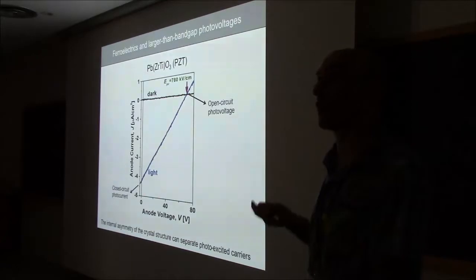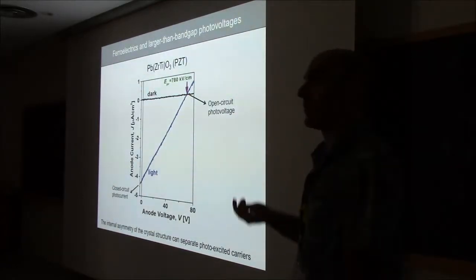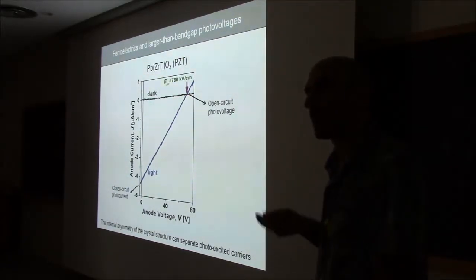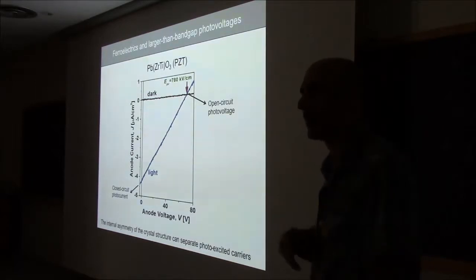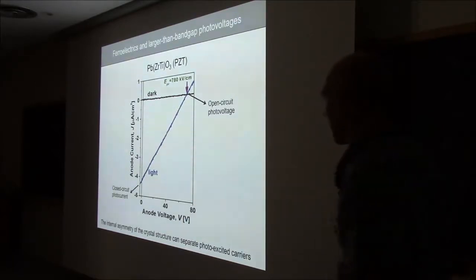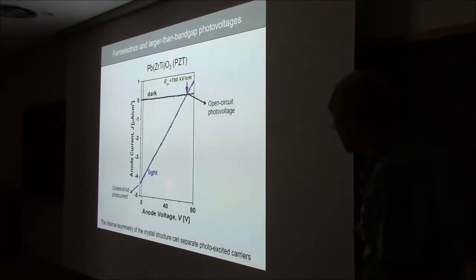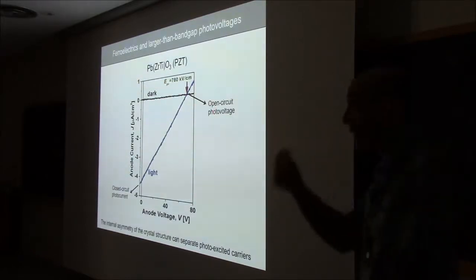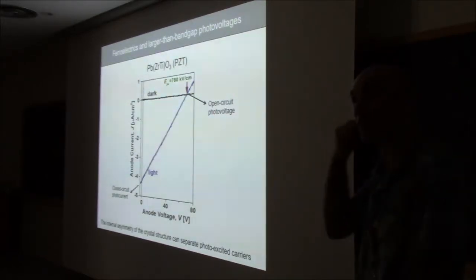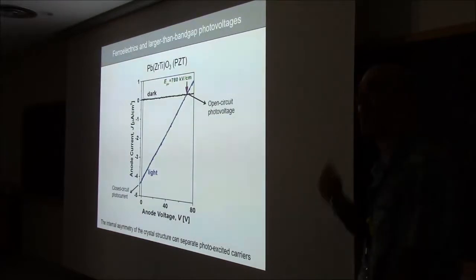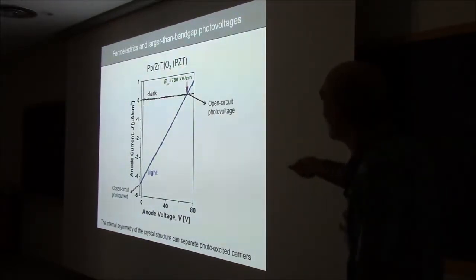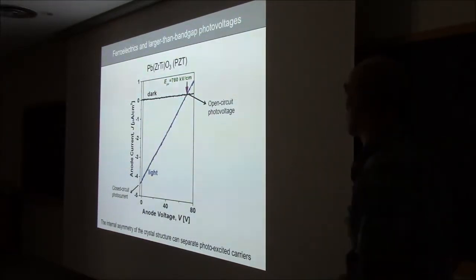This experiment was done also about 30 years ago with lithium niobate on a single crystal, and I think they measured 1,000 volts. Huge. That's obviously bigger than the band gap. And in fact, if you divide the voltage by the thickness of the film, and remember this is a very cheap geometric trick, then the photoelectric field can be huge, right? Almost 1 million volts per centimeter.